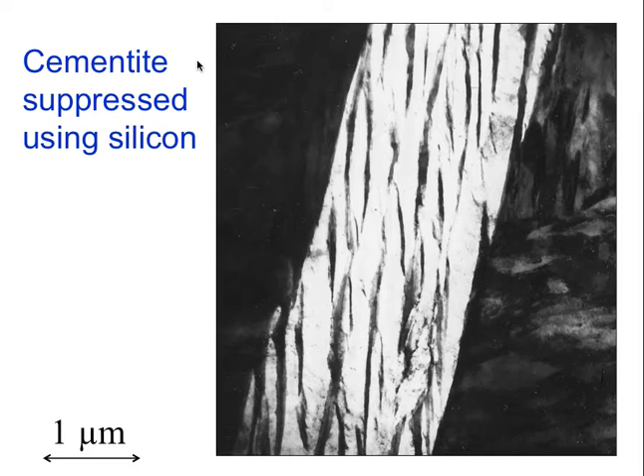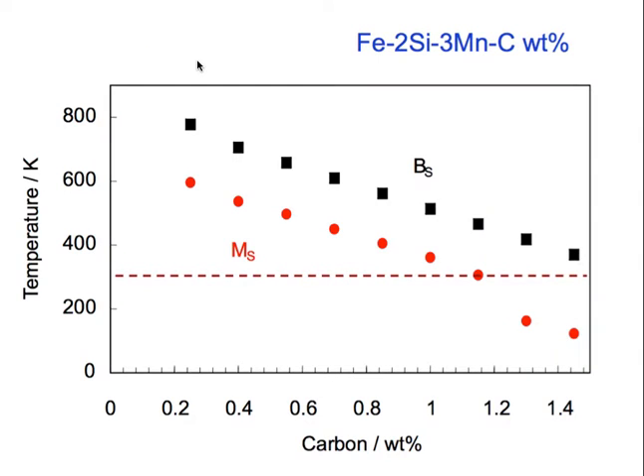What's the lowest temperature at which you can get bainite? I can suppress the martensite start temperature. In everything you've learned, give me some numbers. 200 degrees C? But it's a fundamental question - could I get it at 0 Kelvin? Let's do the calculations. All the theory is there. I've got to make sure both martensite start and bainite start temperatures are suppressed together. These calculations show the dash line is room temperature. Basically, I could get bainite at room temperature.